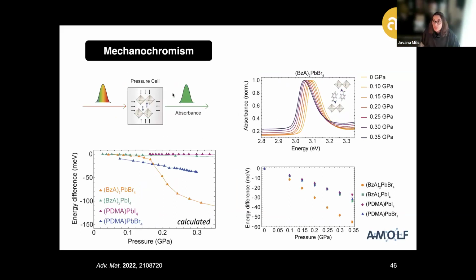Both the UV-vis absorption and photoluminescence emission, which in case of these layered perovskite systems typically feature these conventional excitonic peaks that then redshift upon exposure to higher pressures, to an extent that is most pronounced for these systems suffering from, or tolerating, the highest structural rearrangement, such as this Ruddlesden-Popper benzylammonium lead bromide-based system.